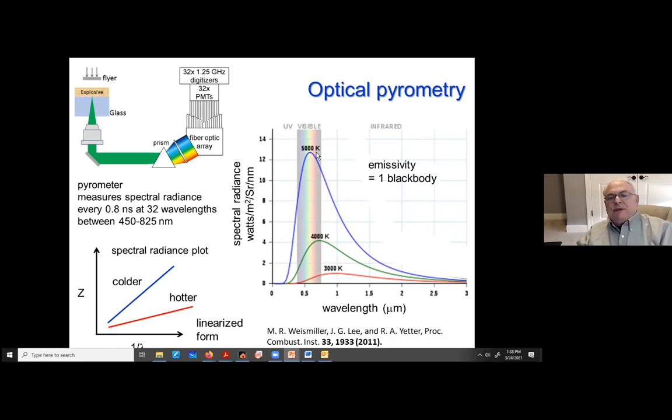The temperature is the shape of the spectrum. The purpose of the emissivity is to learn how much of the material has reacted in a given time. So if you start out with transparent stuff, it has minimal emissivity. But once it's burning and you're making free electrons and plasma, it has high emissivity. So with this measurement, you can get some measure of the reaction progress through this intensity, and you can also get a measure of the temperature.